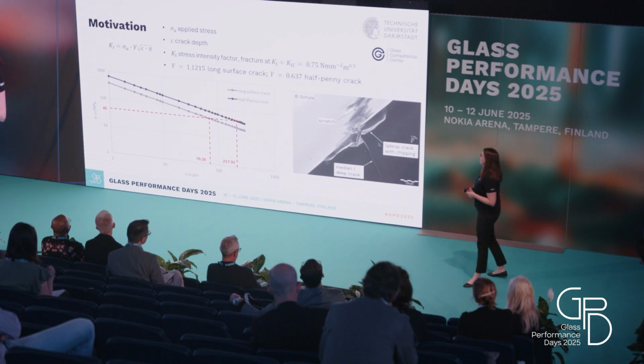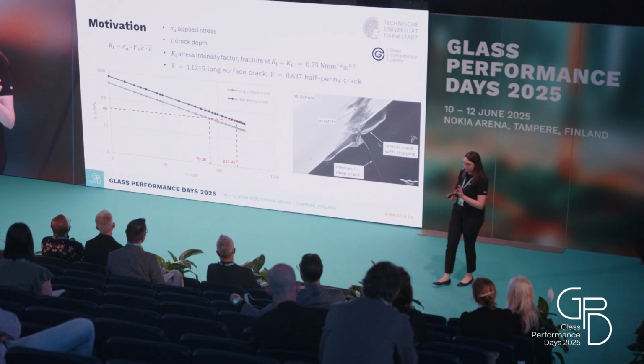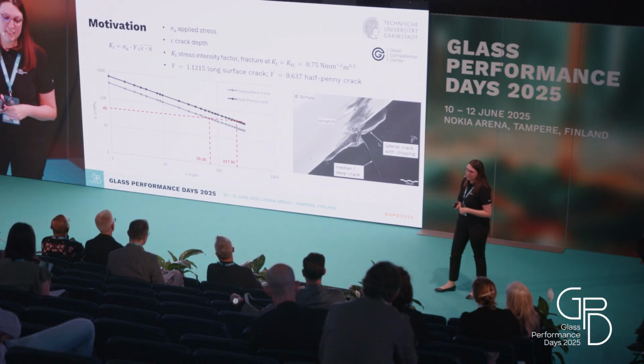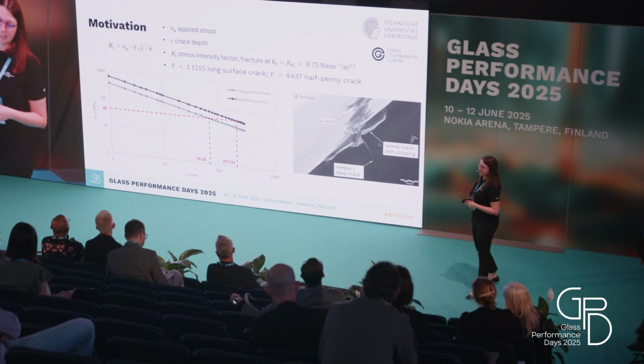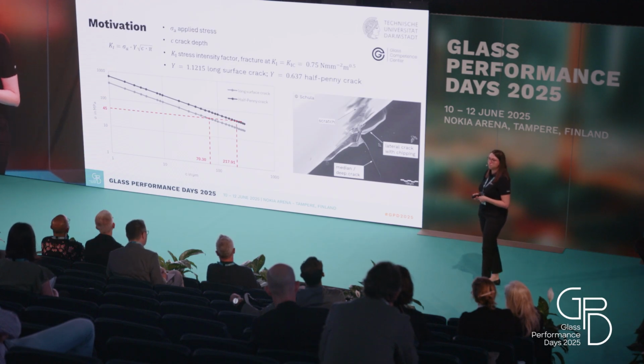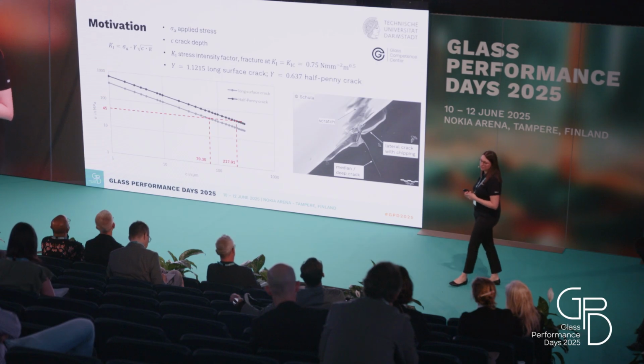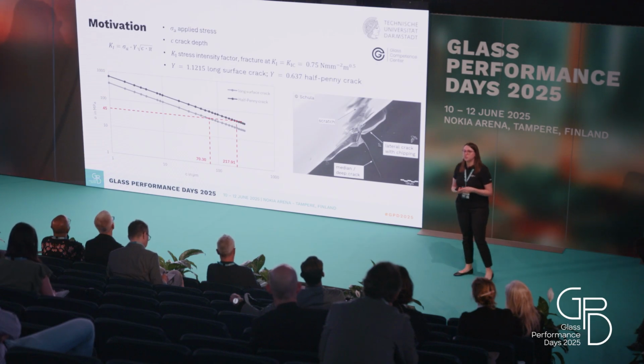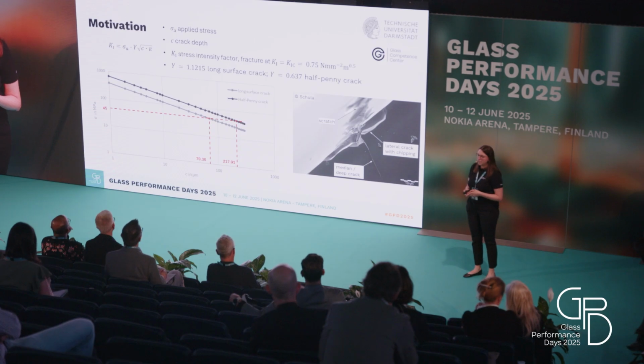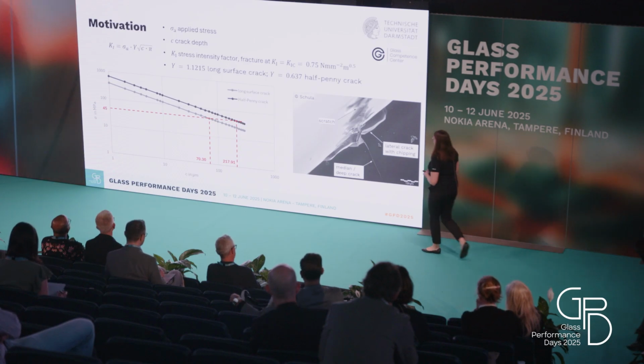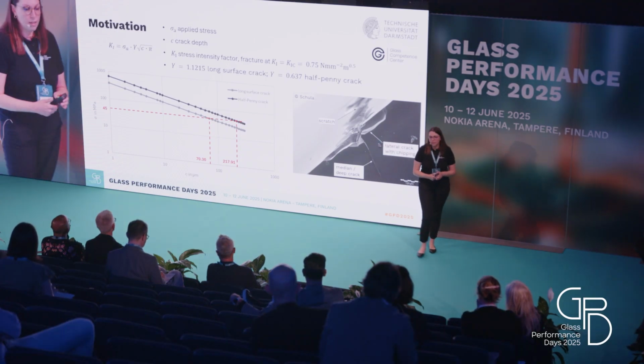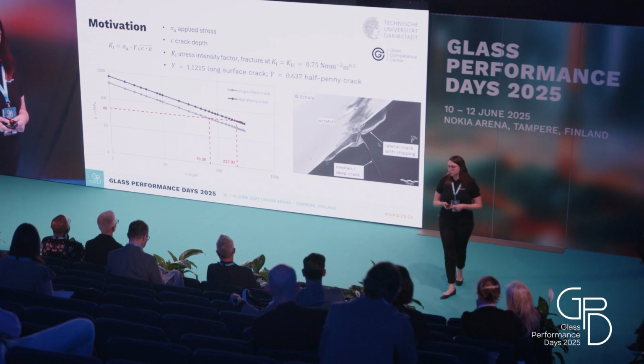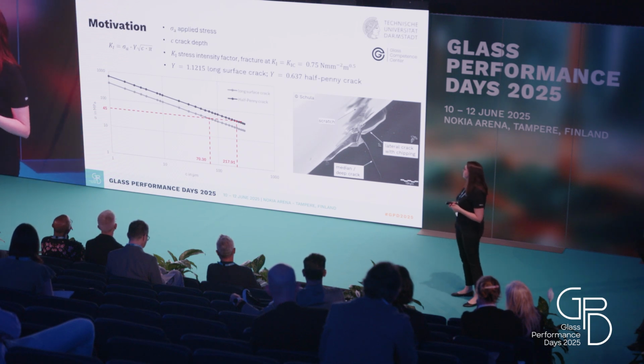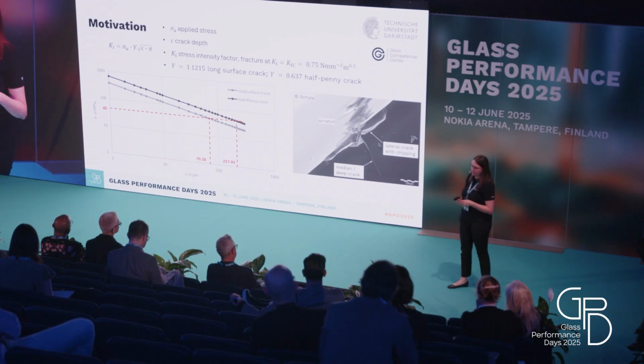And having a look at the fracture mechanics, we see this very short formula, which says that K1, which is the stress intensity factor, can be calculated from the applied stress. This is the stress that acts perpendicular to the crack flanks. A geometrical factor, which is dependent on the geometry of the crack, and also the depth of this median crack. In the graph, we see two gray lines. These are two different geometries for the crack. So we have the long surface crack and the half penny crack shown here.